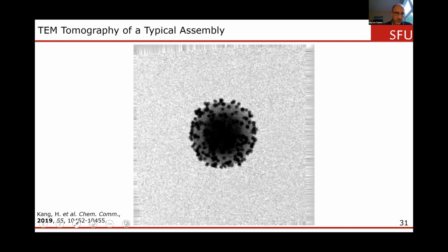To show you what those look like, I'll turn off the laser pointer and take a look at this. This is a tomography image. We've done multiple tomography images looking at the gold, and it is coating on multiple surfaces. We're not getting one gold per thiol because of electrostatic repulsion between the gold particles, and there are many more thiols on the surface than that. But we are able to cover a range of the surfaces, and we can tune that loading. We've shown that you can come back and tune what that loading is.